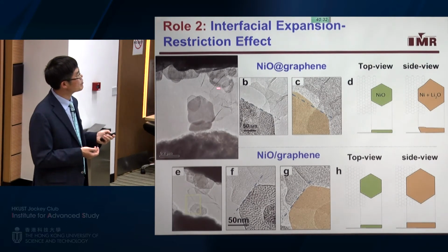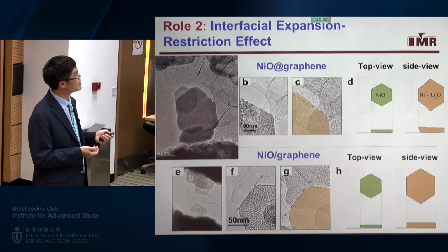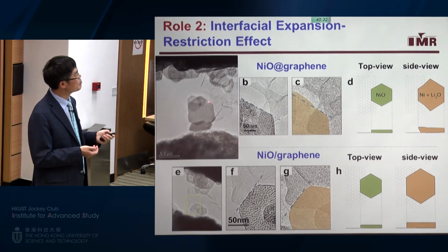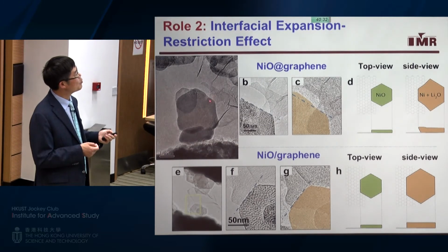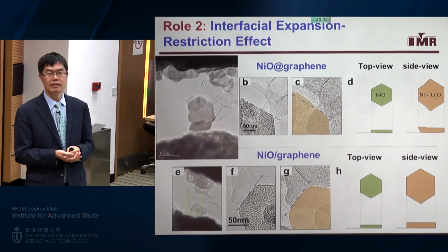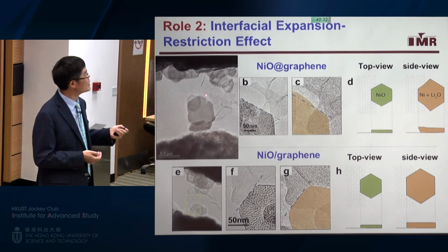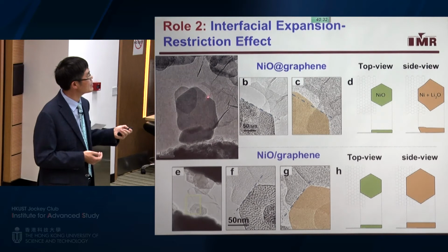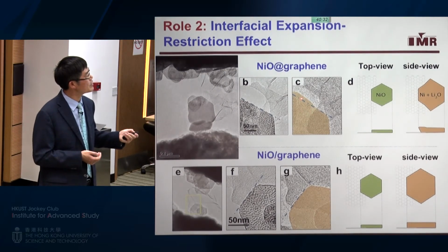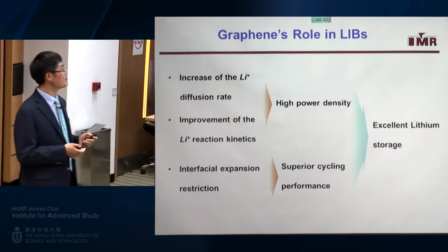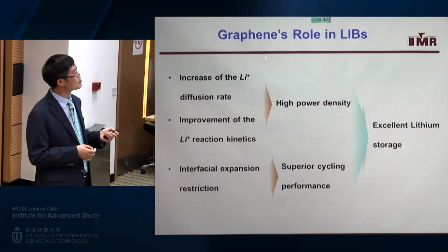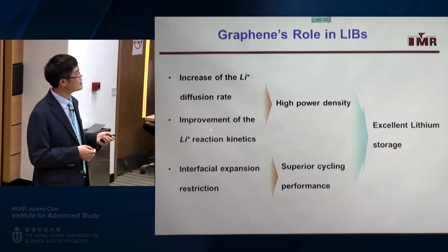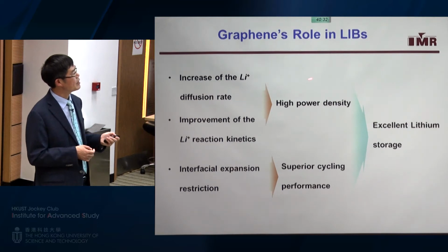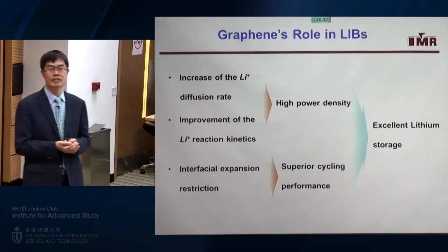So this is a piece of graphene. This is a piece of nickel oxide nanosheets. You can see with the interaction between the oxide and the graphene, the volume change has been restricted very clearly. In this free nickel oxide place, you can see the volume change increases, and the volume is increased here. So therefore, we know that graphene's role in lithium-ion batteries or supercapacitors is to increase the lithium diffusion rate, improve the reaction kinetics, and control the interfacial expansion. Therefore, we can improve the performance of lithium-ion batteries.